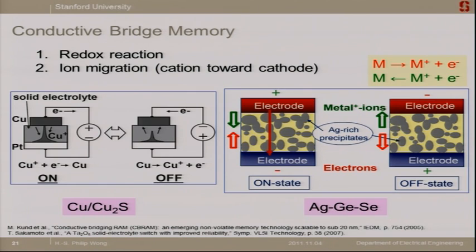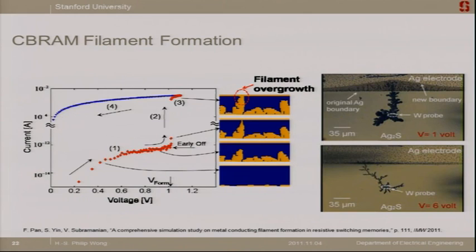You dissolve the copper in here, and the copper migrates and forms a filament, and when it touches, it forms a filament. When it goes the other direction, you dissolve the copper into the electrolyte, and you disrupt the filament. This is a picture from Vivek Subramaniam on this campus showing formation of a silver filament. You see this silver filament during programming, and here's some modeling showing filament growth. This is kinetic Monte Carlo modeling showing filament growth until it touches. Once it touches, it goes through a lateral growth.